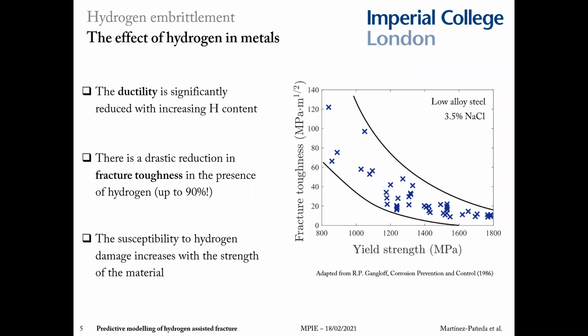One is that hydrogen is effectively compromising decades of metallurgical research. We have developed high performance materials, but we cannot use them. And the second one is that high strength steels very significantly widen the range of environments where hydrogen is problematic. With these more susceptible modern materials, very little hydrogen content is sufficient to trigger failures in many applications and sectors where we never heard about before.